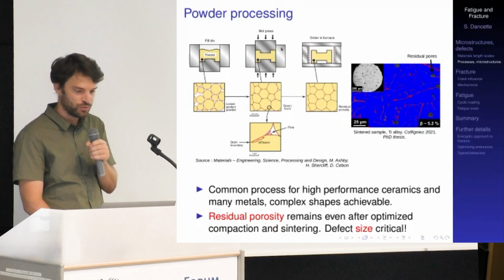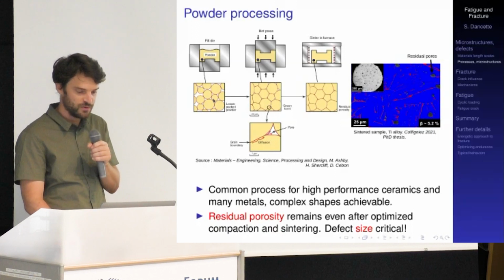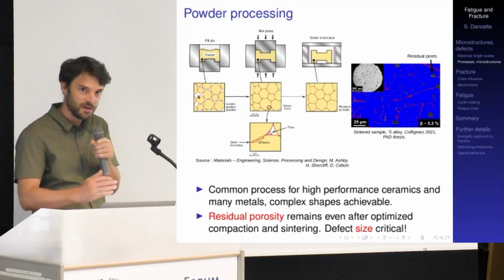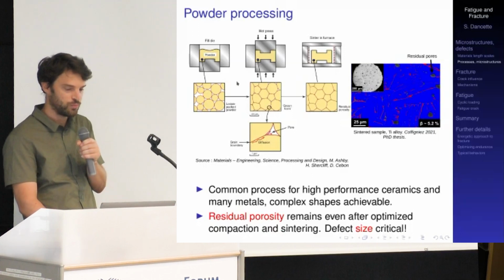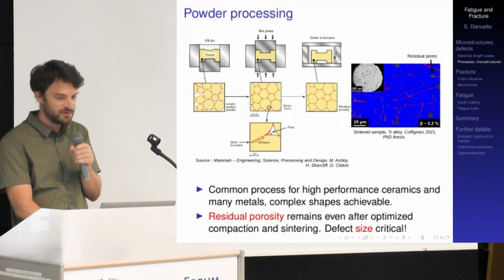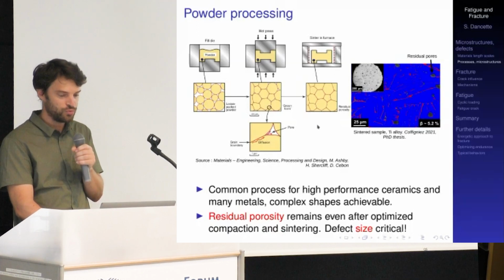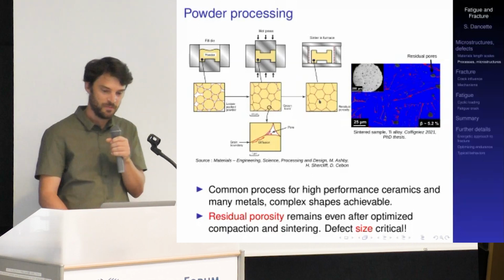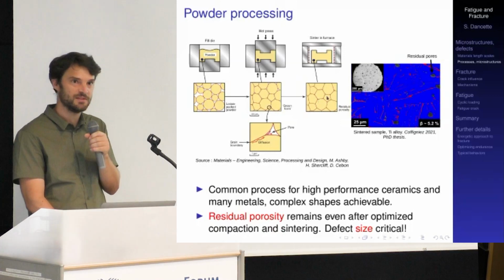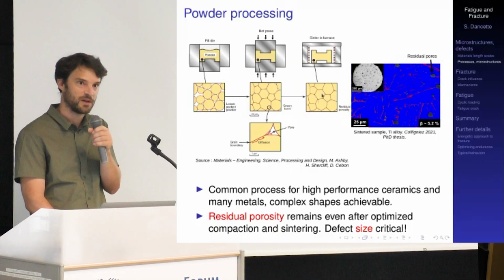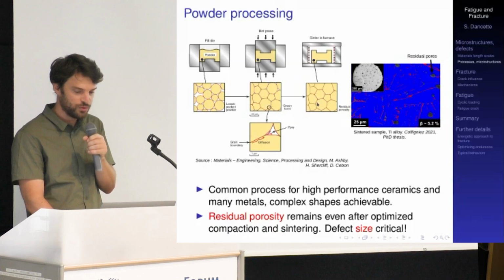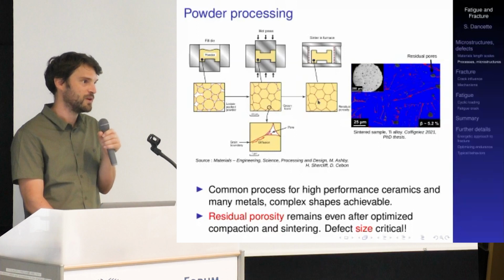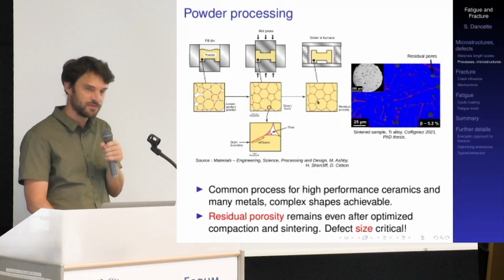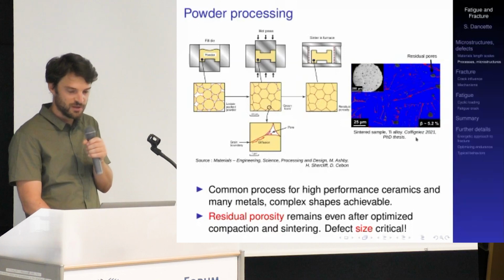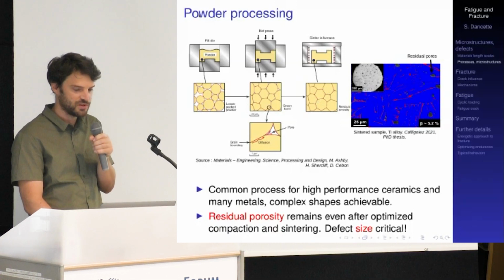So with this compaction process, you start from powder with a lot of free volume between the particles, and thanks to the compaction and thanks to temperature in a furnace, then diffusion will allow you to achieve a material that is close to compact. But again, this material is in fact only close to compact. It is not 100% compact. So the residual pores, residual voids that you may find at the triple points, for example, in this microstructure, you have an example here on the right in this picture, which is a titanium alloy that was produced by such a kind of powder processing.